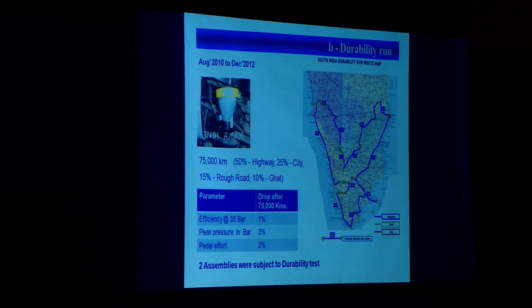In August 2010, in the initial validation stages, we ran it for 75,000 kilometers, out of which 50% was in highway, 25% in city conditions, 15% in rough road, and 10% in Ghat conditions. And this was the run route map. What were the parameters which were measured after the 75,000 kilometers test? Efficiency at 35 bar, then peak pressure in bar, and the pedal effort.